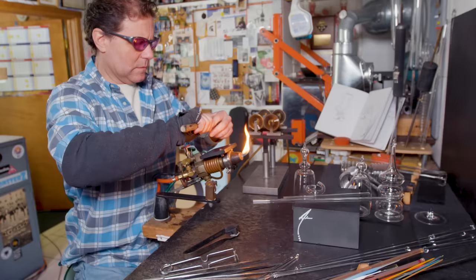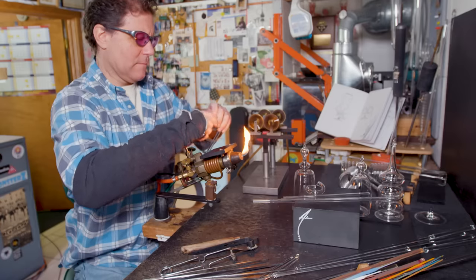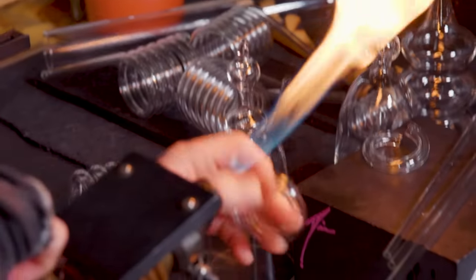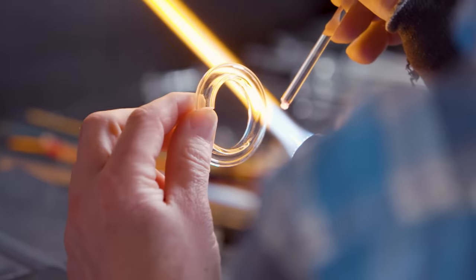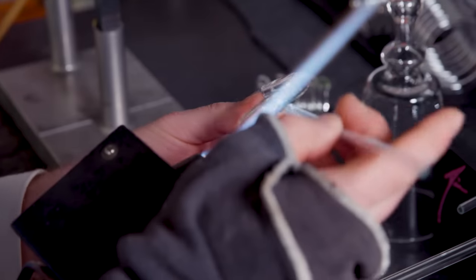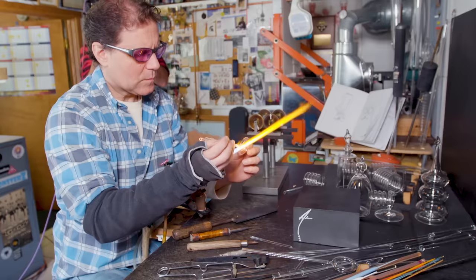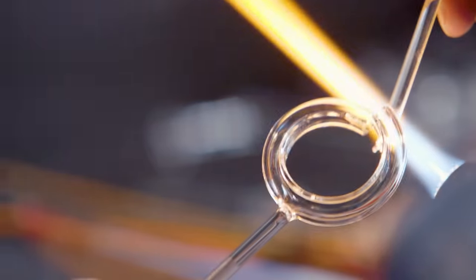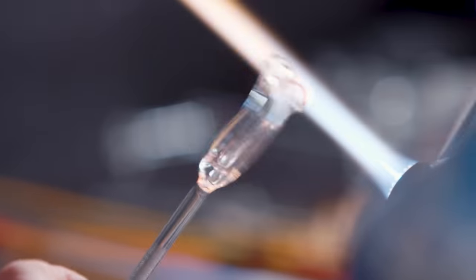I'm cutting the coils to give me sections of workable size. I cut the coils using a tungsten carbide blade, a really hard metal, so it scratches the glass and with pressure on the backside causes the glass to break in an even way. So now I'm just pulling a hole in the ring because I need to be able to blow this together when I seal these ends off. And I take my piece of six millimeter and I seal that temporary blow pipe.